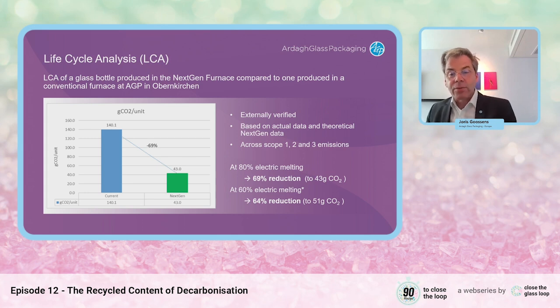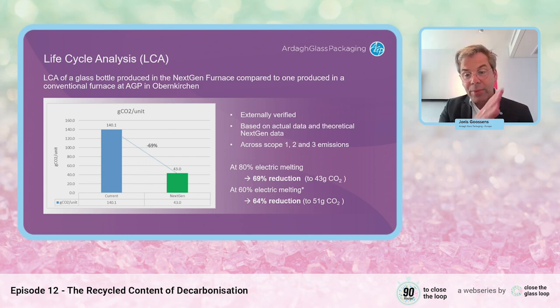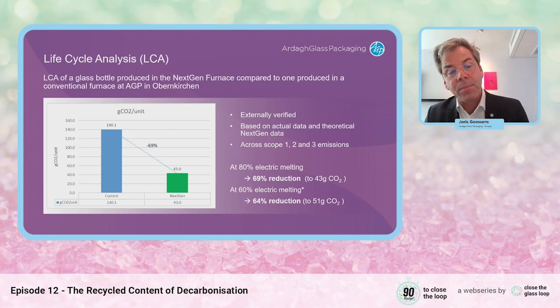And of course, it's about results. If you look at the CO2 emission, the reduction of CO2 emission in this new furnace, it's immense. If you compare it to the earlier furnace, producing the same bottles with the same pool and the same cullet in the same site, then at 60% electrical melting, we already reduced CO2 emission by 64% per bottle, scope 1, 2, 3.